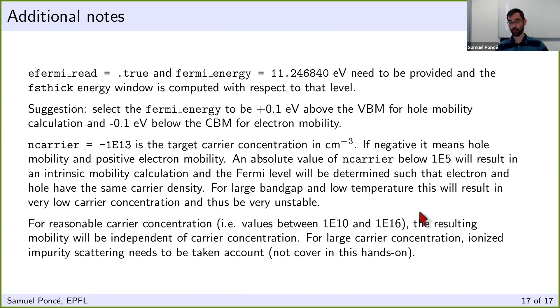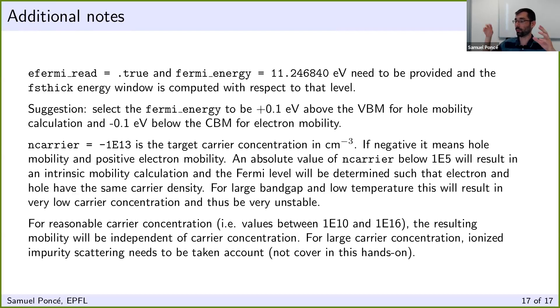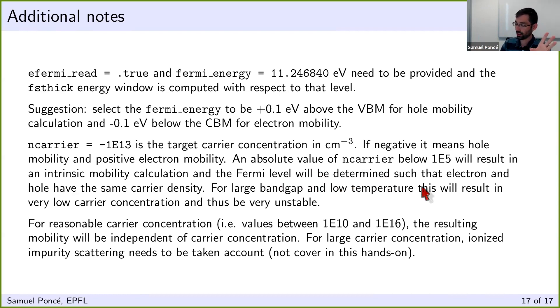If the carrier concentration is below 10^5, the code understands you want an intrinsic mobility calculation. In that case the Fermi level is placed in the middle of the band gap such that electron and hole have the same carrier density. However, this requires Wannierizing both conduction and valence bands together, making the calculation more expensive. The recommendation is to use the carrier input and compute conduction and valence separately.